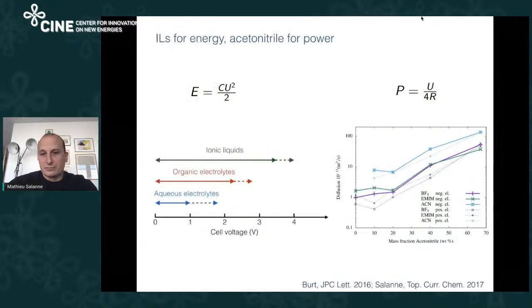Then, of course, you have other aspects which are playing a role. As I told you at the beginning, we look at the operating voltage. And in that case, ionic liquids are much better because you can reach 3 or even 4 volts in some cases, while organic electrolytes are limited to something around 2 volts. So the energy density is better, but the diffusivity is much smaller in ionic liquids because they are a bit sluggish, and you can have 2 orders of magnitude difference in the dynamics in the system. And so in the end, the power will be much larger in organic